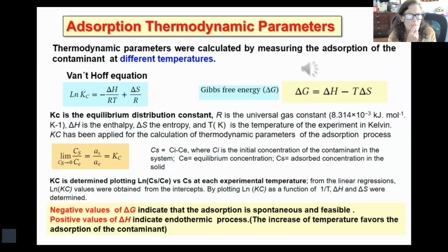From the adsorption experiments at different temperatures, we determined the thermodynamic parameters of the adsorption process. We applied Van't Hoff equation to calculate enthalpy and entropy from the equilibrium distribution constant, and also we calculated the Gibbs free energy. Negative values of delta G indicate that the adsorption is spontaneous and feasible.